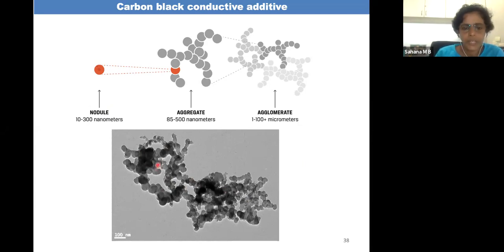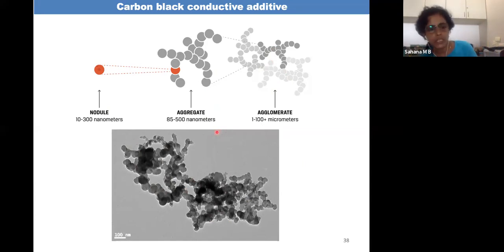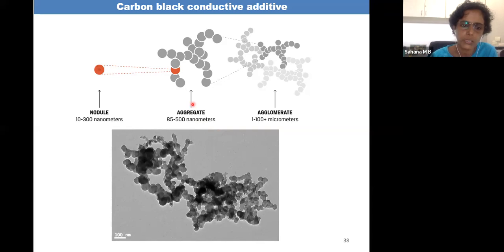Now, basically, when we purchase carbon black, it is an agglomerate of 1 to 100 micrometer size. By applying force, we can de-agglomerate them and make them aggregates of 85 to 500 nanometers, which are made up of nodules of 10 to 300 nanometers. It is not possible to separate out these single particles separately because of the very small size of carbon black. The minimum size we can get is the aggregate size.